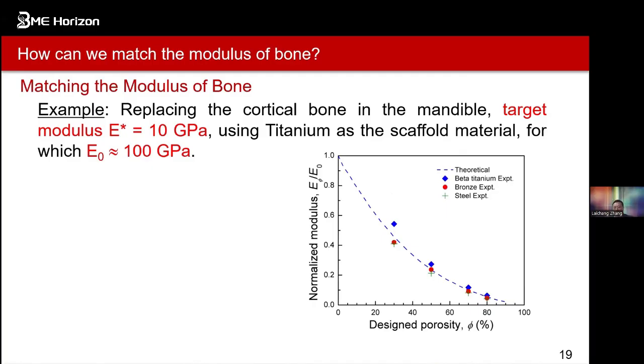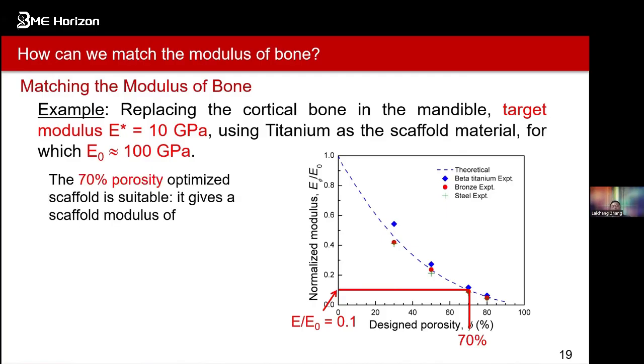So then from this chart, we can get some information. How can we make this Young's modulus close to our implant, for example, for the medical implants. So we can roughly get these things. So you see this target one is 10, and the overall is 100. So 10 to 100 is roughly 0.1. So that's what we can get from the chart. We can say 0.1. Then we get this to find how much of the porosity the design should have. So then we can read off that it's roughly 70%. So then we can say, hey, this 70% porosity optimized scaffold is suitable for replacing our bone, to match the Young's modulus of the bone. So that's how this works for the titanium from the graph. We can get the data very easily.